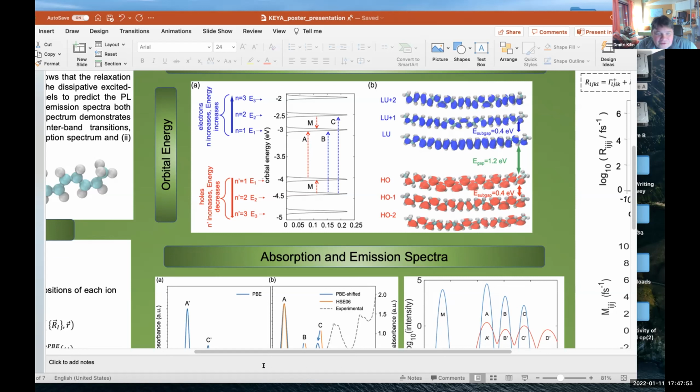Now, how do you interpret the blue orbitals? Oh, are they just a bunch of little potential wells? No. The strand itself is a potential well, and orbitals are just eigenstates of a particle in a box.